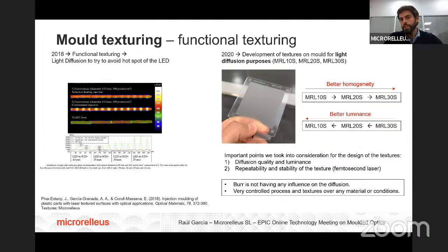But 2 years later, we began to study the possibility to create some roughness in the mold using the femtosecond laser to achieve this light homogeneity. The important points we took into consideration for the design of textures were diffusion, quality, and luminance, but also repeatability and stability of the texture. That's why we used the femtosecond laser.